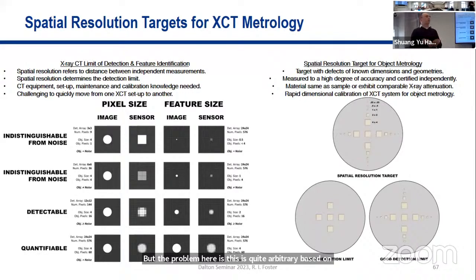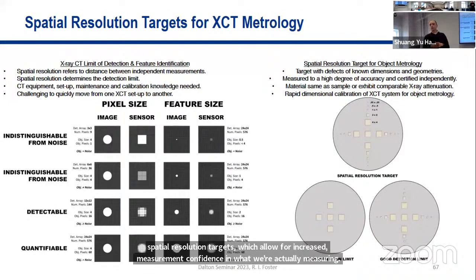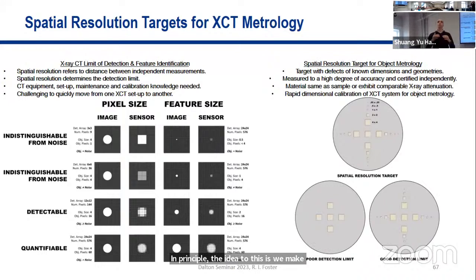What we want to try and do is actually develop a more robust way that can be used regularly for calibration and also for object detection. This is where we've been collaborating with our collaborators in Alethea, with Dr. Tristan Lowe and his colleagues, to actually look at developing what are called spatial resolution targets, which allow for increased measurement confidence in what we're actually measuring. In principle, the idea is we make some form of disk or object, which we can put known defects into of known sizes. We then know, for example, if we put an object or defect of 10 microns into our target and then measure this in CT, if we can see that, we can know that our detection limit can be 10 microns.